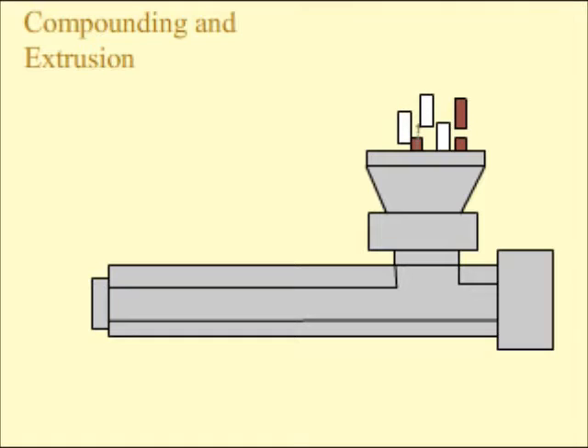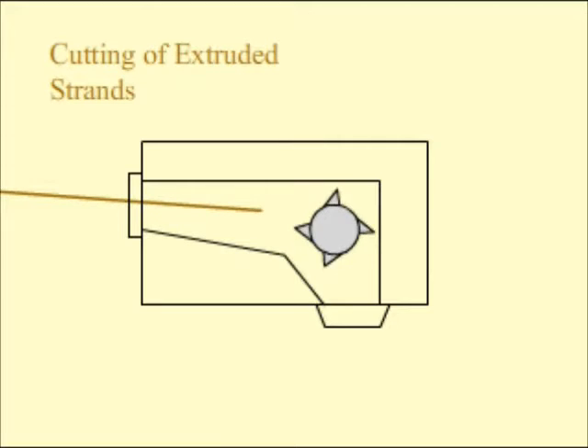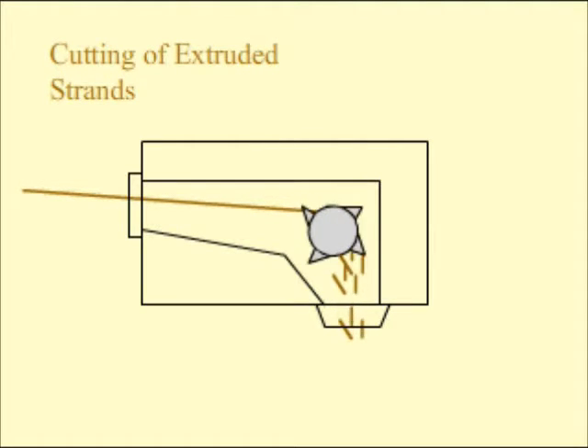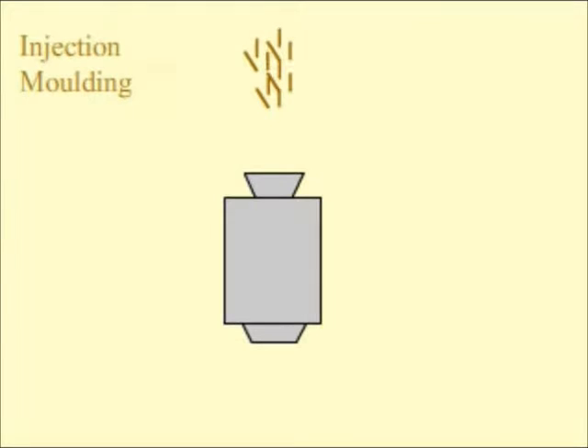Secondly, there is the compounding and extrusion of the bio-composite. The polymer and the coffee filler were compounded at 190 degrees Celsius in the macro extruder according to the desired compositions, where the bio-composite was extruded twice to ensure more homogeneous mixing of the polymer matrix and coffee filler. The extruded strands of bio-composite were then pelletized for injection molding process.